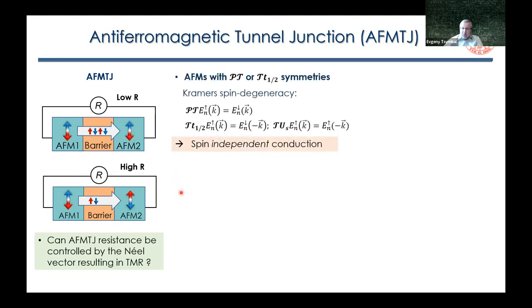So unfortunately, most of the antiferromagnets have bands which exhibit Kramers spin degeneracy, because most of the common antiferromagnets have T-tau-one-half symmetry. So this is time reversal symmetry combined with one-half unit cell translation symmetry. Or we can have PT symmetry, as I've mentioned before. In both cases, this symmetry enforces Kramers spin degeneracy, which means that all the bands are doubly degenerate.